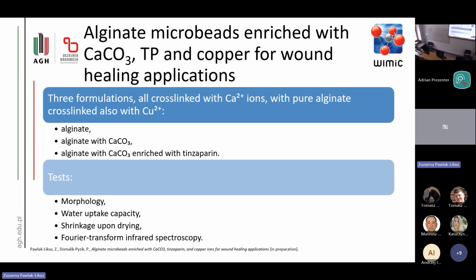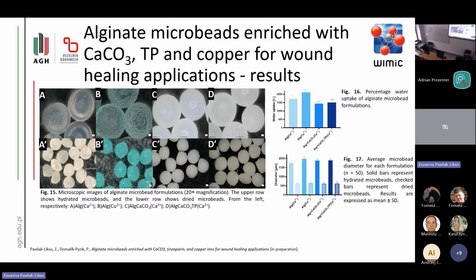So we made 3 formulations, and all of them were cross-linked with calcium ions. It was pure alginate with calcium carbonate, and alginate with calcium carbonate and tinzaparin. But we also cross-linked pure alginate with copper ions to test what it will change. And the tests we did were morphology, water uptake capacity, shrinkage upon drying, and FTIR. And here are our results.